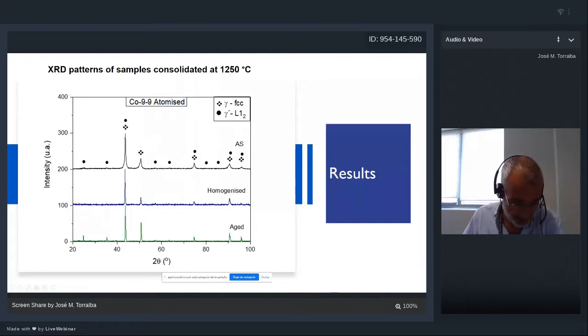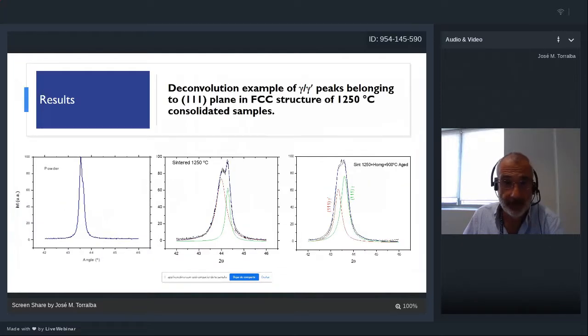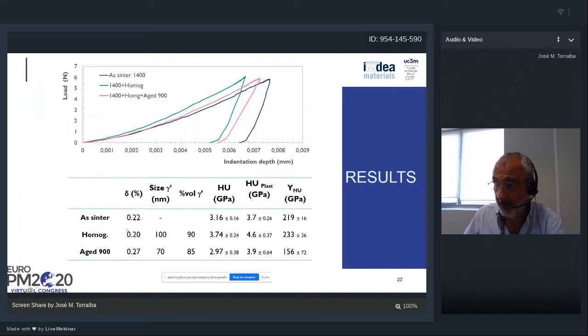For this reason, we have to deconvolute. We have to produce a deconvolution in order to distinguish the peak of the gamma and the peak of the gamma prime in order to calculate this lattice parameter and then the misfit for each material.